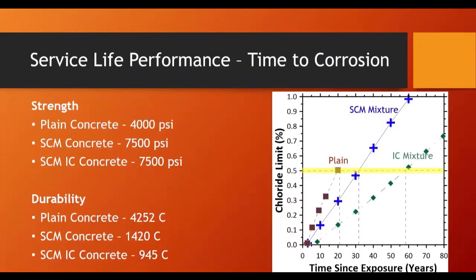Now, if we look at the time to corrosion of these mixtures, and we do some diffusion calculations, not assuming any of these mixtures have cracked, which we already saw the plain conventional mixture did crack, which provides a superhighway, we see that the first mix starts to corrode at about 20 years. The mix with the slag, we go out to about 35 years. The mix with internal curing and slag goes out to about 60 years before we start seeing corrosion.